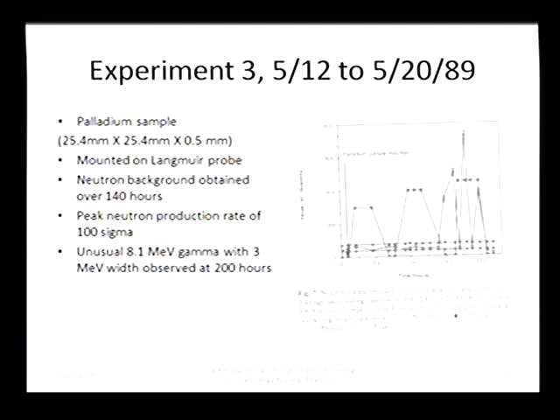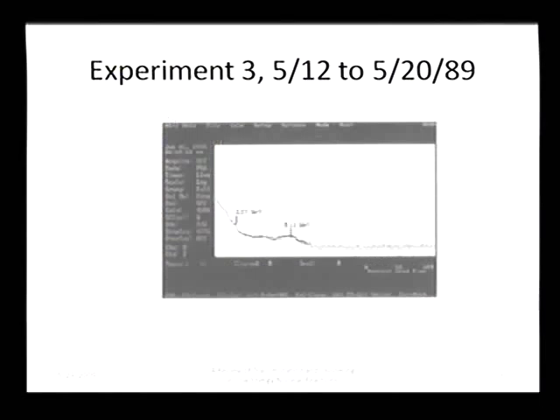But what was interesting with this experiment is that about 200 hours into the experiment, that would be this particular burst here of neutrons, we had our sodium iodide detector set up to look at gamma spectra. And this is a spectra that we saw coming off. We had a broad peak, which is not unusual for sodium iodide. Sodium iodide is not a terribly efficient spectrometer material, and it's known for broadening peaks, so that's not unusual.